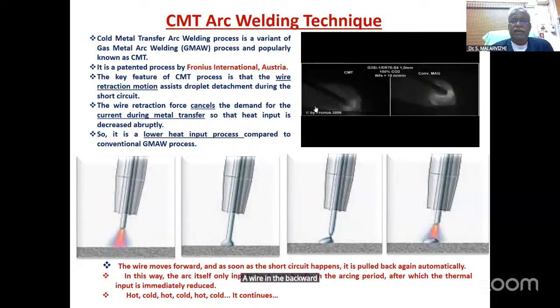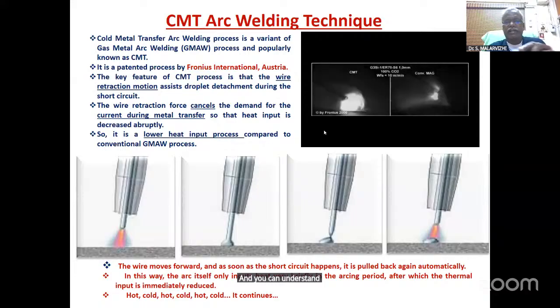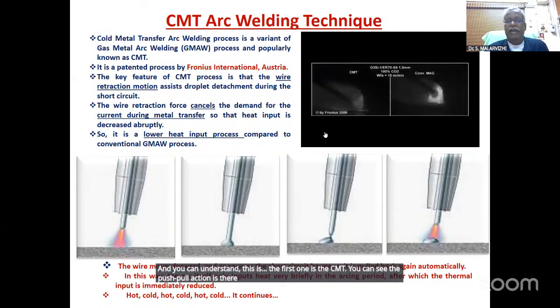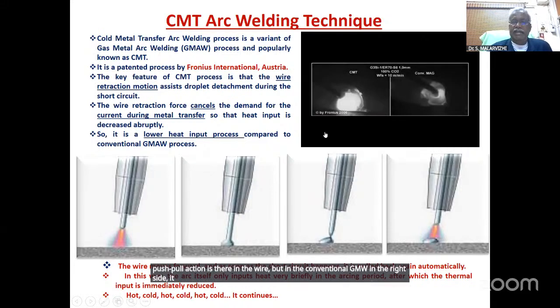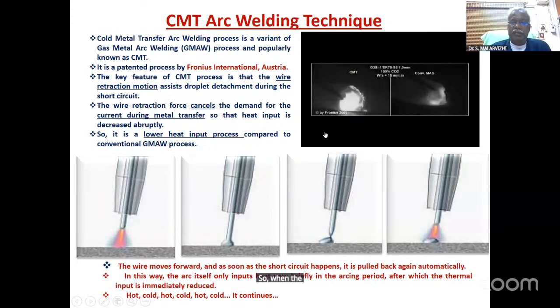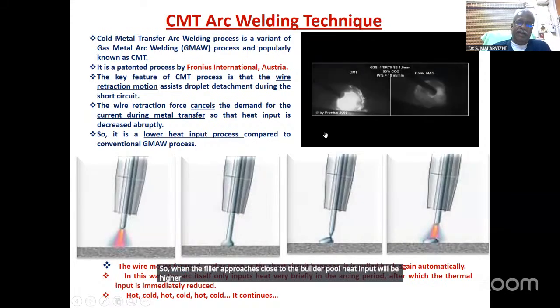So this is happening. If you see these clippings, you can understand, the first one is the CMT. You can see the push-pull action in the wire, but in the conventional GMAW, on the right side, it is only in one direction. So when the filler rod approaches close to the weld pool, heat input will be higher. When the filler rod is retracted, the heat input is reduced here.